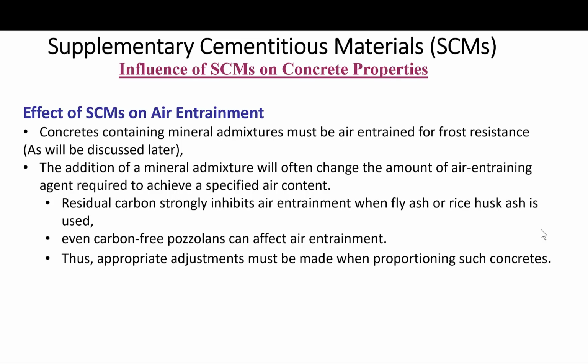The addition of a mineral admixture will often change the amount of air entraining agent required to achieve a specified air content. This is usually due to residual carbon within these admixtures, which strongly inhibits air entrainment, especially when fly ash or rice husk ash are used. But even carbon-free pozzolans can affect air entrainment, so appropriate adjustments must be made when proportioning such concretes. Again, trial mixes are key in order to understand and verify the effect of any addition to the concrete mix.